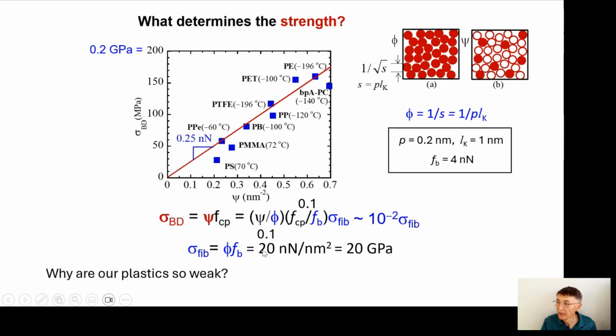So why is it so weak? Due to these two factors. First of all, it's not in the fiber straightened chain limit. Secondly, the chains pull out instead of breaking. So each of these factors will introduce a factor of 10. And that's why what you observe is only a much lower strength, as you see here.